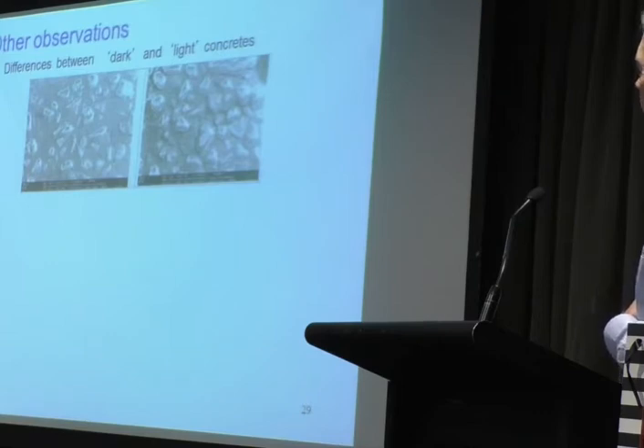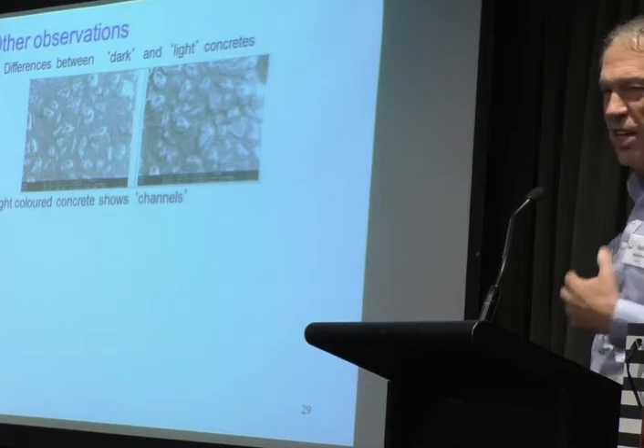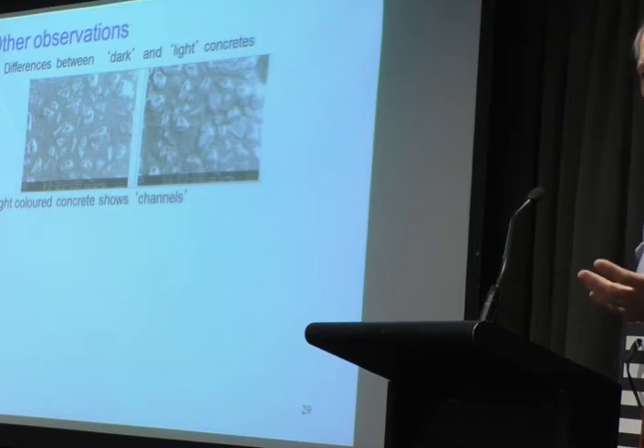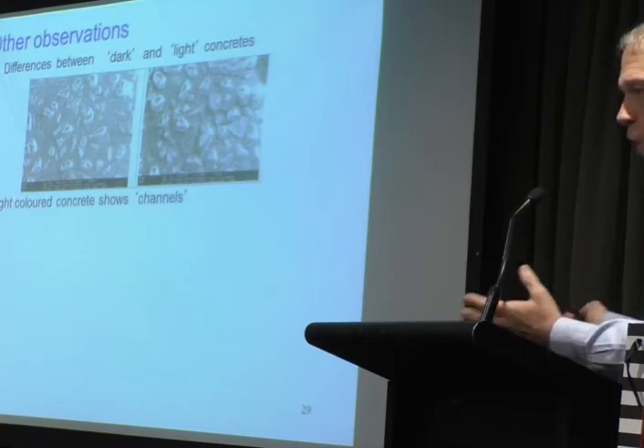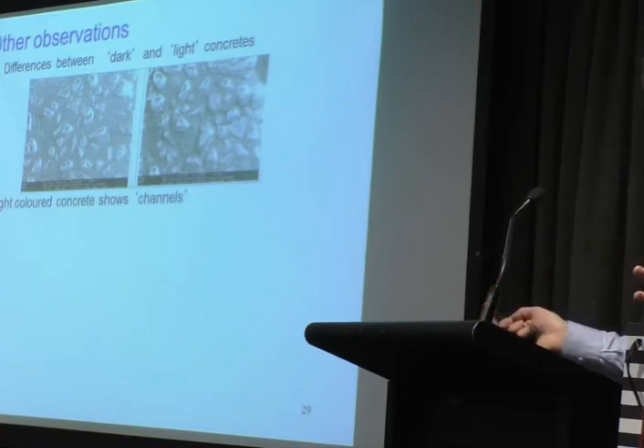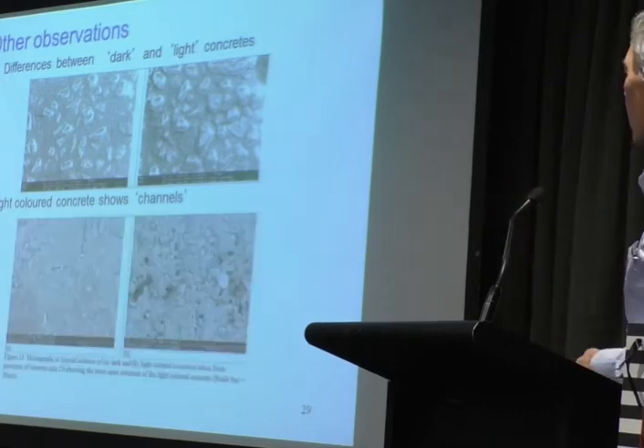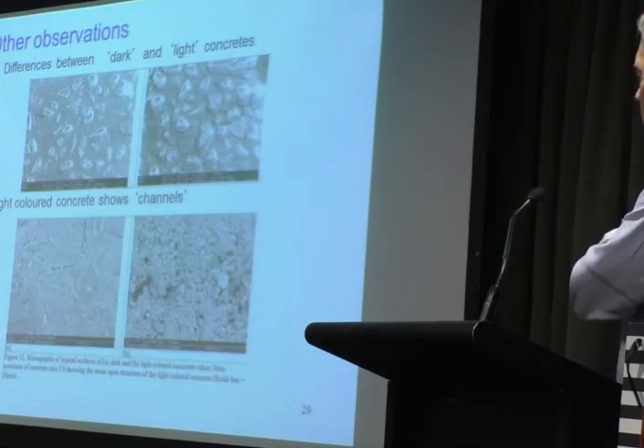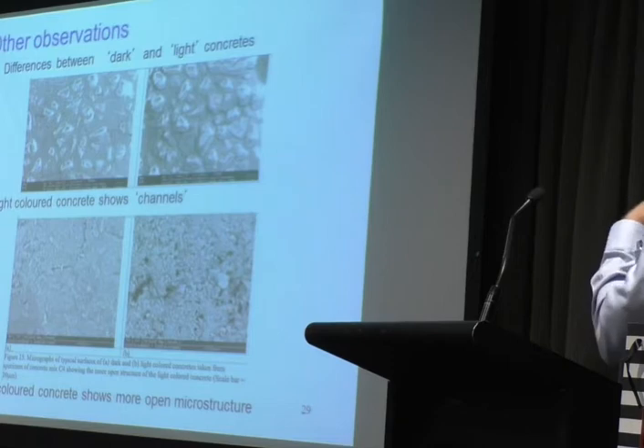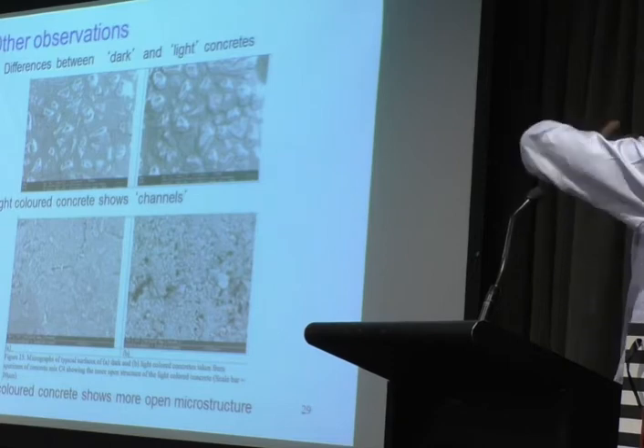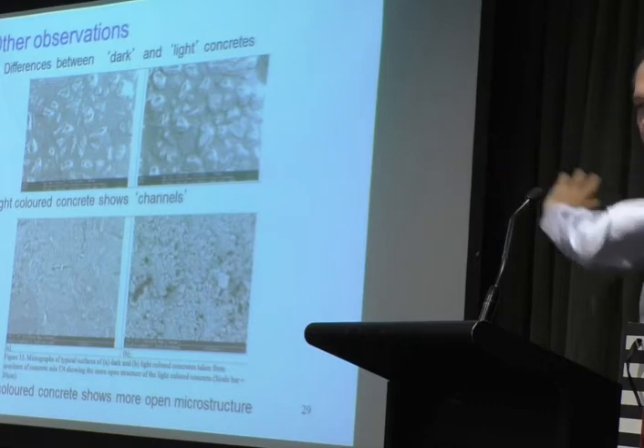Dark on the left side, light on the right. You can see the light-coloured concrete shows channels. It's much more porous than the dark. So this was the same concrete mix, same sample, but just out of the dark part and the light part. And if you're under the microscope, you see the same sort of thing. So what has actually happened is that oxygen was able to diffuse into that mix and change the colour.